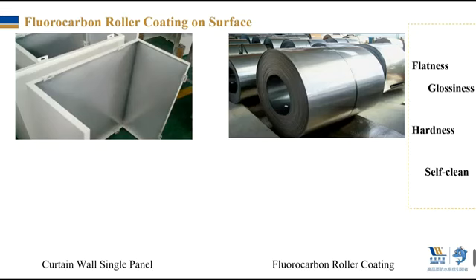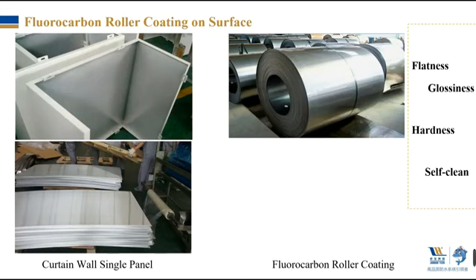However, the traditional aluminum must be folded first, and then the spraying and baking process is performed after the adding of steel corners. After being folded, the aluminum panel is unevenly heated. Its flatness and glossiness will not be at the same level as aluminum coil used for the fluorocarbon roller coating process. Besides, in the spraying process, the direction of coating is vertical to the surface of the aluminum panel, but in the roller coating process, the direction of coating is parallel to the surface of the aluminum coil. The hardness and self-cleaning property of the fluorocarbon coating applied will be greatly improved. This is why the decorative effect of Jobatech's aluminum surface external wall system is more beautiful than that of traditional aluminum curtain wall.